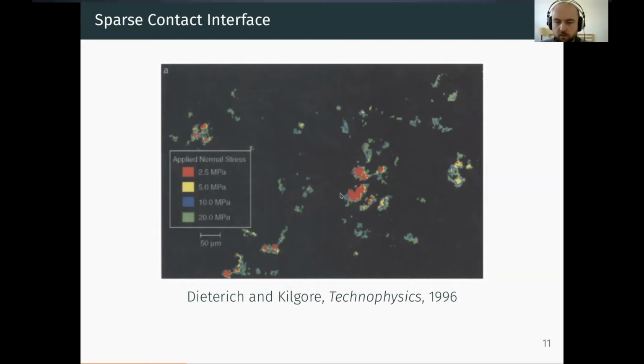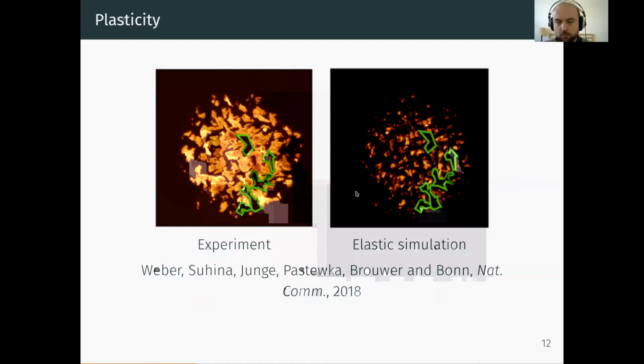So you might think that since the true contact area, the area where forces are transmitted, is so small compared to the apparent contact area, the local pressures must be really high. And they are actually high enough that they cause irreversible damage or irreversible deformations in the bodies in contact. And we've known this for a while, but I find those experiments by Daniel Bonn and his team to be really visual to show this. This is the experimental true contact area for a rough sphere on top of a flat surface. And this is a corresponding simulation that uses the true roughness measured in the experiment, but assumes elastic deformation. And you can see that it completely misses the mark on the true contact interface.